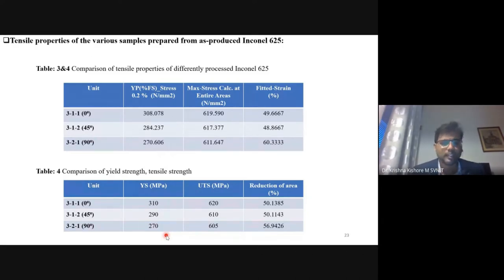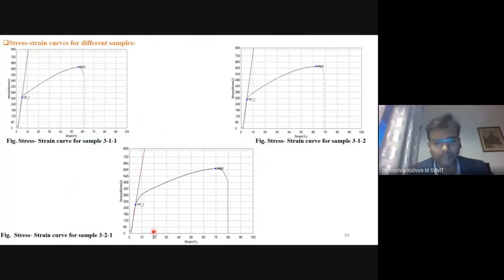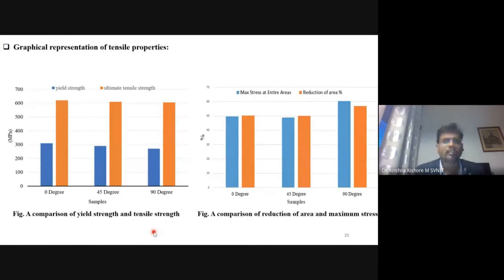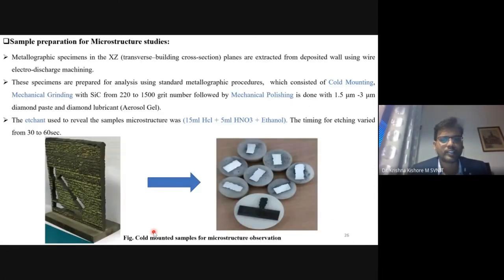microstructural changes. Even though I'm saying that the yield strength is nearby, within plus or minus 20% error, the microstructural property, if you see, is quite deviating. And these are some tensile sample drawings which I want to show. And we have calculated the percentage of area, UTS, yield strength, these things.